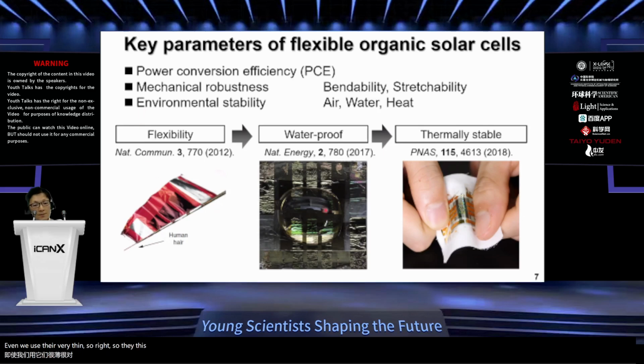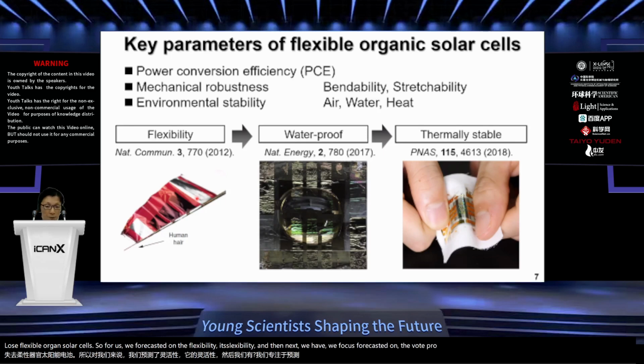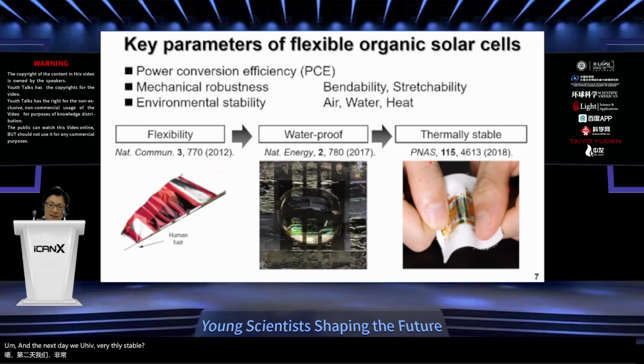These bottom figures show the progress of our very thin, ultra-flexible organic solar cells. First we focused on the flexibility, then next we focused on the waterproof properties. And next we achieved very thermally stable organic solar cells. That enables thermal processing to adhere our solar cell devices onto textiles using hot melt processes. This achievement was made by Xiaoming several years ago. So this is very good work.